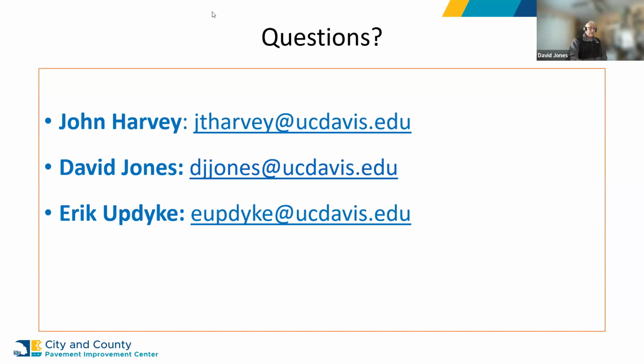Okay, there you go. So you can do a pretty simple investigation, understand the materials you've got, run that unified soil classification system on it, and then be able to come up with a strategy around those materials. But even if you've got 4 inches of severely distressed hot mix over a fairly marginal material, it's got some plasticity, it's got a high fines content, you could do a 10 to 12-inch treatment with a recycler, and put a 2-inch surfacing on the top of that, or even less. If it's lower traffic, you can get away with a chip seal. That'll work as well.